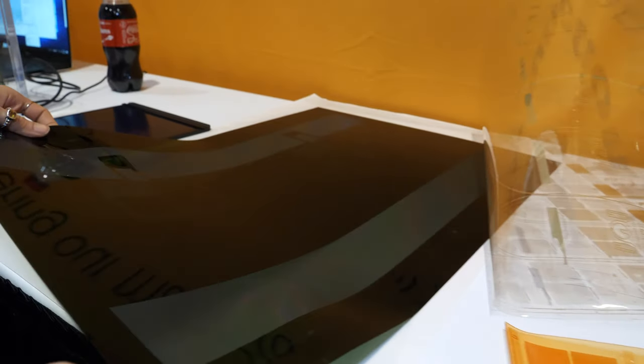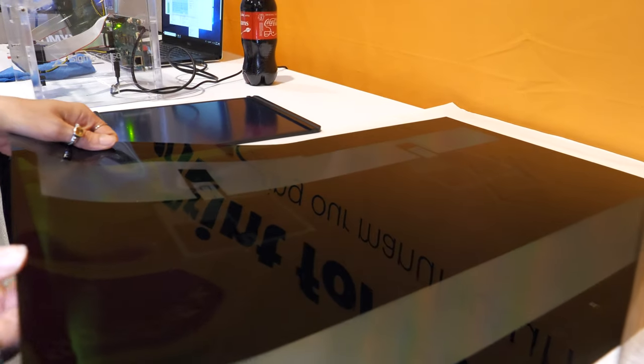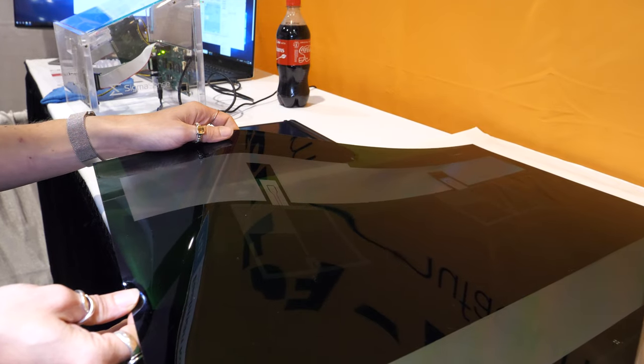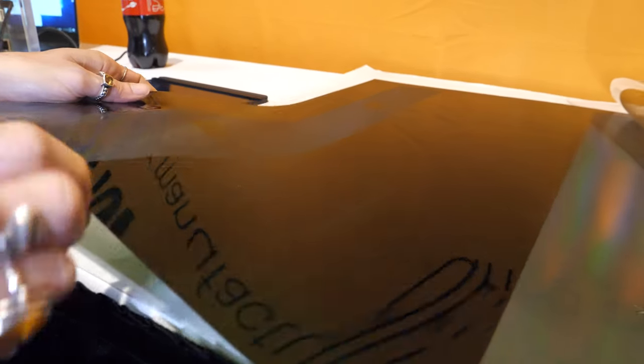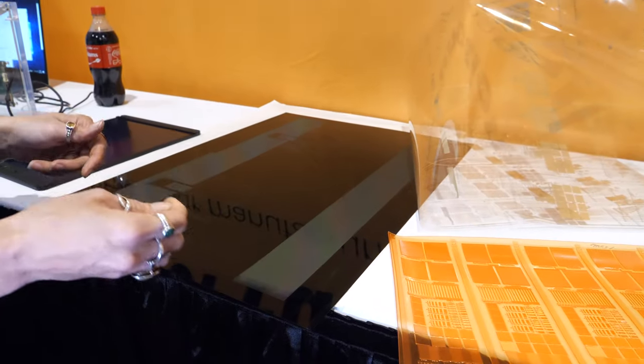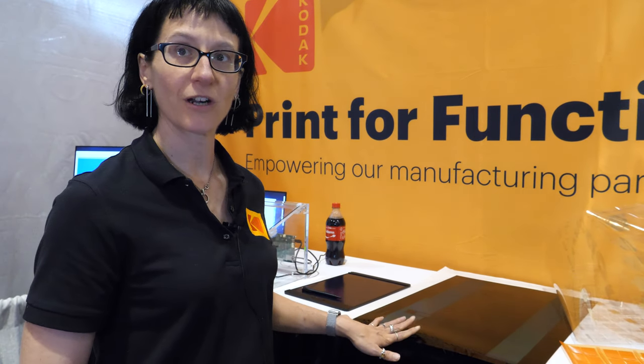This is what's used to image the printing plate. It's called a TIL — T-I-L — or a thermal imaging layer. It is patterned with our high resolution imager by laser ablation using Kodak's trademark square spot technology. The feature size that can be resolved in the thermal imaging layer, which is effectively an optical mask layer, is 2 microns. You then use that 2 micron image mask layer to transfer the pattern to the flexographic plate — the image resolution goes down a bit, and then transferring to the page, the feature size increases a little further.